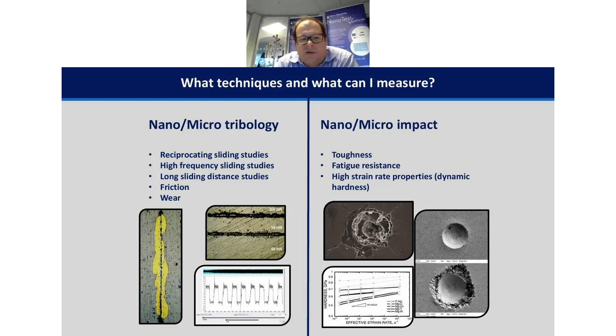Moving along the strain rate scale, the strain rates associated with indentation testing and scratch testing are pretty low, but a lot of materials are subjected to very high strain rates in their real world application, and it's very useful to be able to replicate those strain rates at the lab scale during the development process, for coatings and bulk materials. With nano and micro impact, we can create single or repetitive very high strain rate contacts to look at toughness, fatigue resistance, and effective hardness at high rates of strain, which we call dynamic hardness.